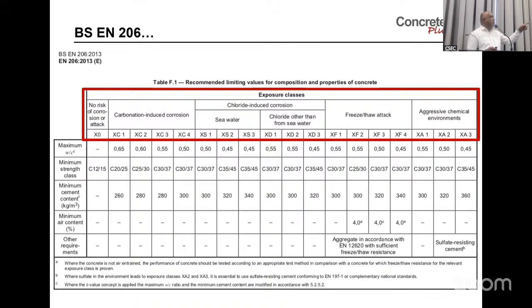It can be no risk. Of course, if there's no risk, you can do as you wish. Because if you don't have reinforcement inside, most of the time water ingress will not be a very critical thing. Of course, there are some other issues, like we get different diseases in our body, but the main issue is corrosion. The second one is carbonation. In carbonation, why are you allowed to go up to 0.6, 0.65? Because the carbonation depth per year is around 1 millimeter. So if you have a 50 millimeter cover, it takes 50 years just to reach there. That's why sometimes you have a little bit of relaxation.